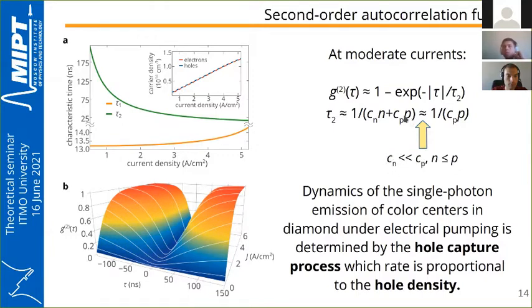And also, in the case of diamond, electron density does not exceed the hole density, as can be seen, for example, from this insert in panel A. Here we see that the electron and hole densities in some point near the color center equal each other.